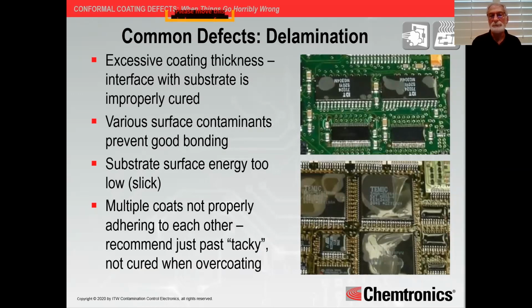Delamination. Delamination is not common, but it does occur. And the bad part is you're generally not going to see this in your manufacturing facility by your inspection team. One of the causes is, again, excessive coating thickness. That interface of the coating at the substrate is improperly cured, or it does not cure at the same rate as the rest of the volume of that coating, and it does not allow for good adhesion with the substrate surface, whether it's a component or the laminate on the board, whatever it may be.